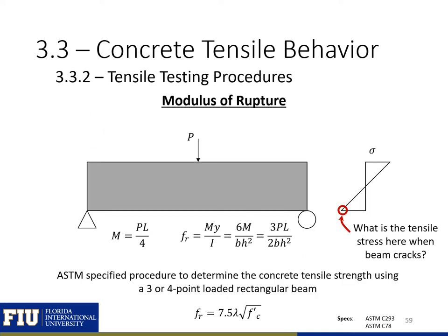There are several different ways that we will use to test the tensile strength of concrete. The modulus of rupture test, shown here, is either a 3 or 4 point bending test as specified by ASTM C293 or ASTM C78. In these tests, a load is applied until cracking of the beam occurs. Because these specimens are unreinforced, cracking leads to immediate failure of the beam. The applied load can be used with simple mechanics relationships to determine the stress in the bottom fiber of the concrete when the beam cracked and failed. This bottom fiber stress is taken as the tensile strength of the concrete.